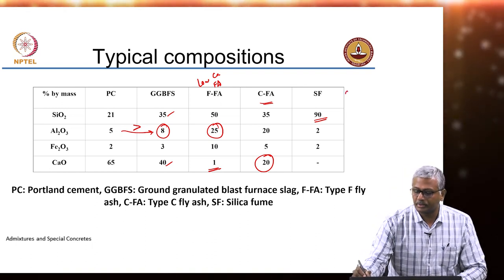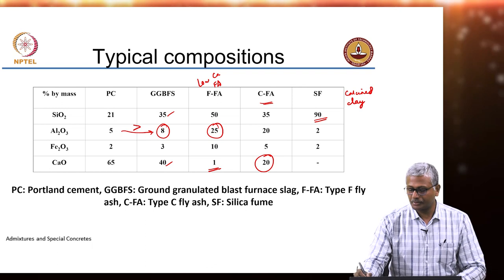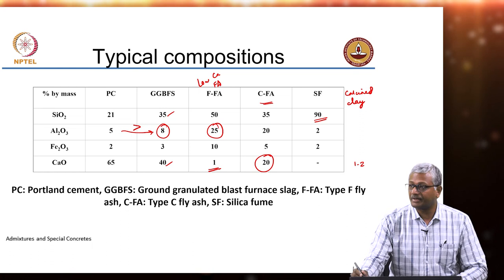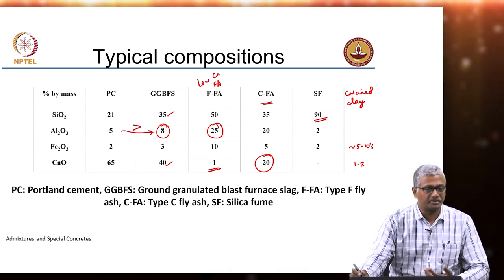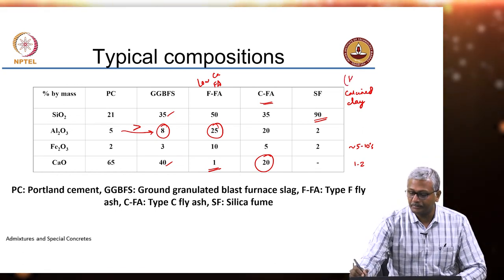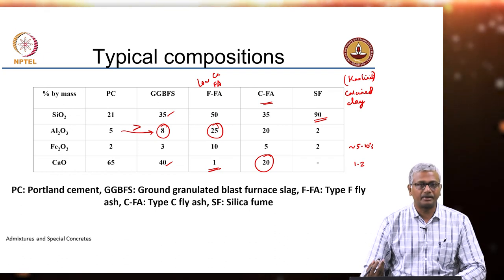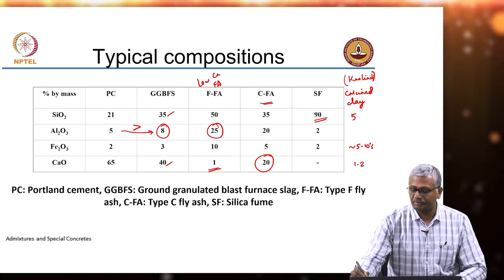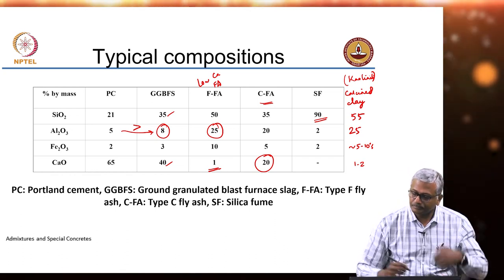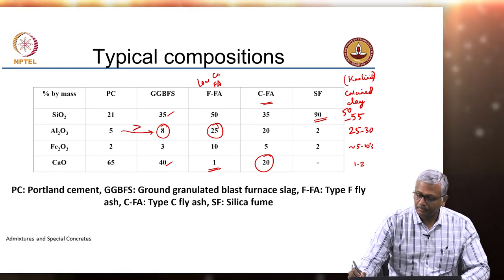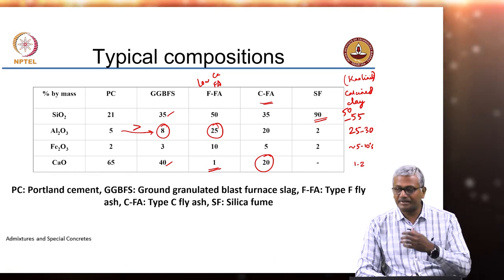For kaolinite clay on the same table, CaO will be close to 0, about 1 or 2%. Iron may be significant, possibly up to 5 to 10%. For kaolinitic clay, there will be almost twice as much silica as alumina — let us say out of the remaining composition, about 50 to 55% will be silica and about 25% may be alumina. So it is an alumino-silicate — mostly we call it alumino-silicate.